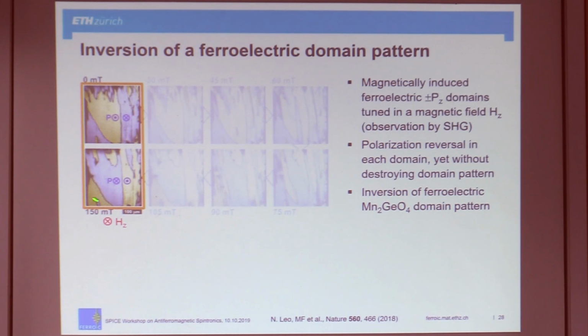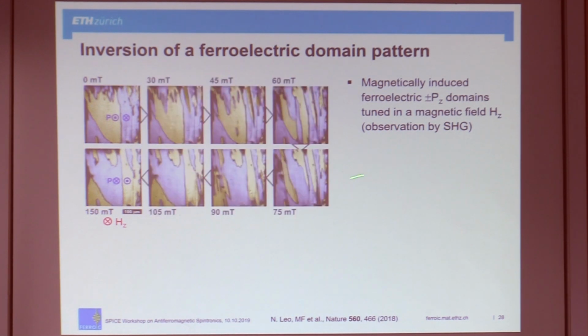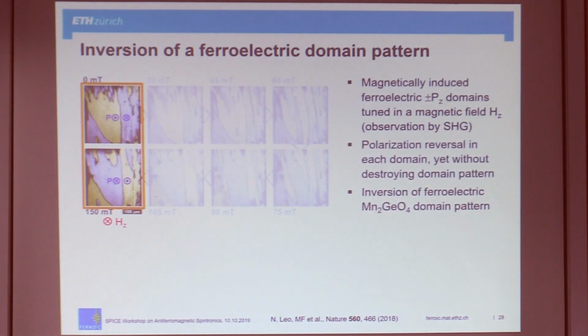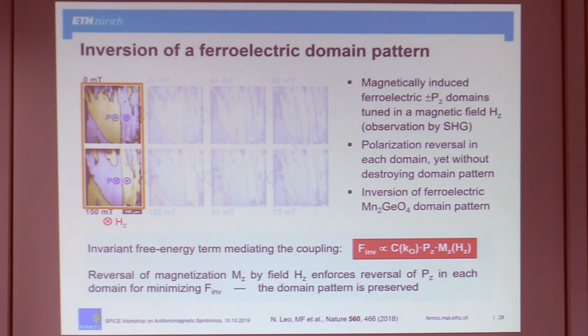It's not perfect, but little details, they match. And the general shape here and this dagger here. So that's quite surprising. Apparently, the domains are rather flexible. They are not pinned. The domain walls are not pinned. But nevertheless, after completing your cycle, you're back at the same domain structure. You have inverted it. How can that be? If you look into this complicated situation with all the order parameters, you find, and I'm not going, I mean, you can do all the maths. That takes you a long time.